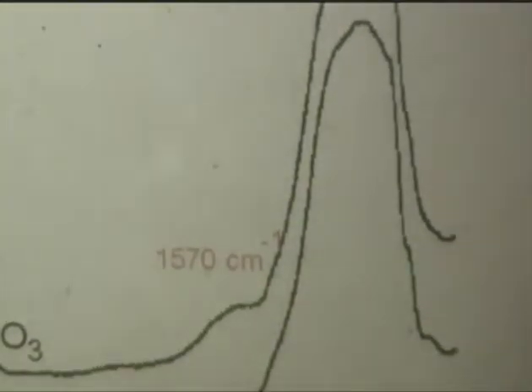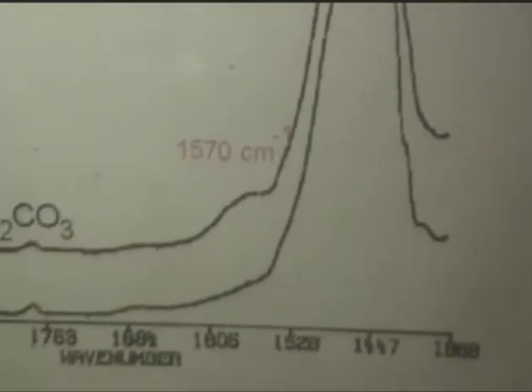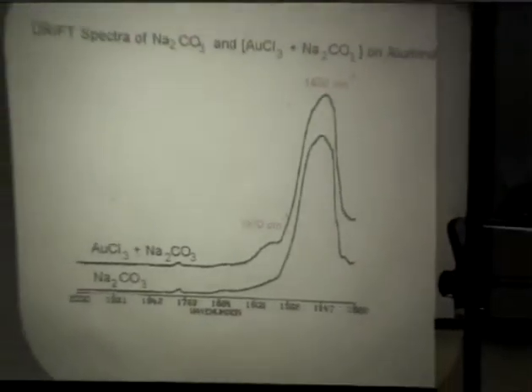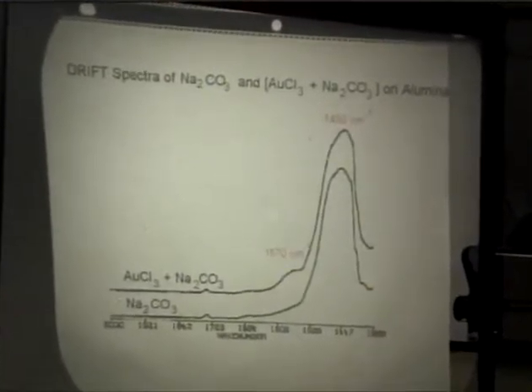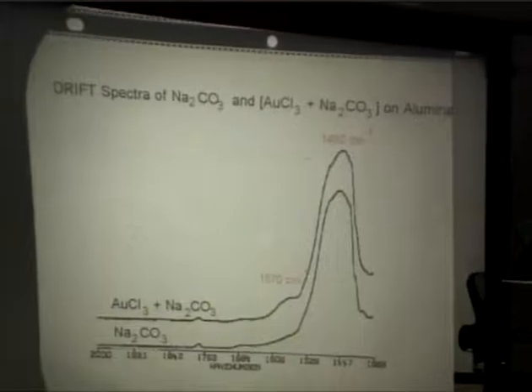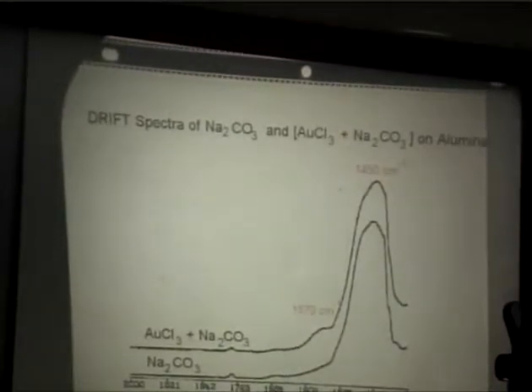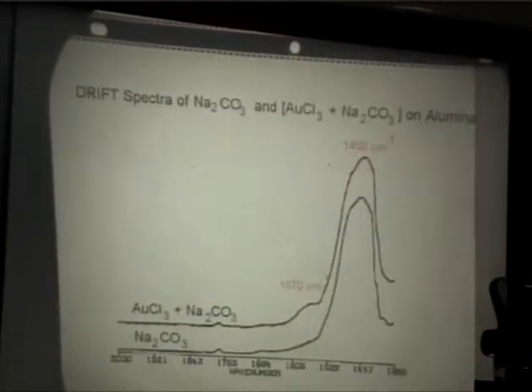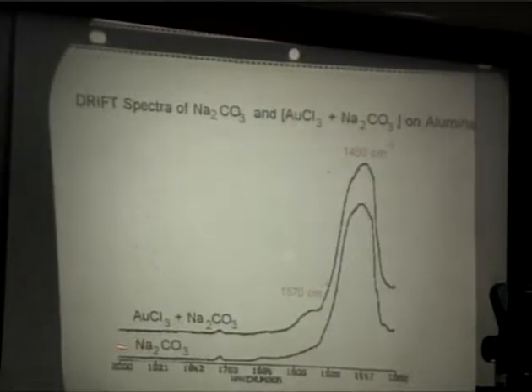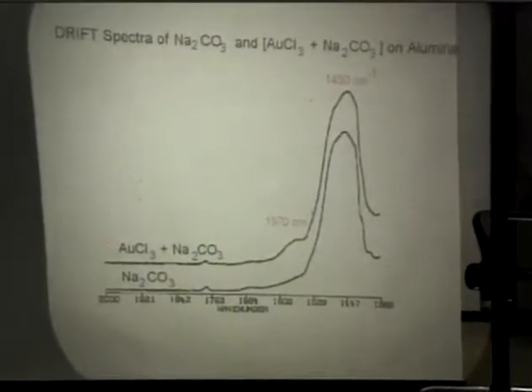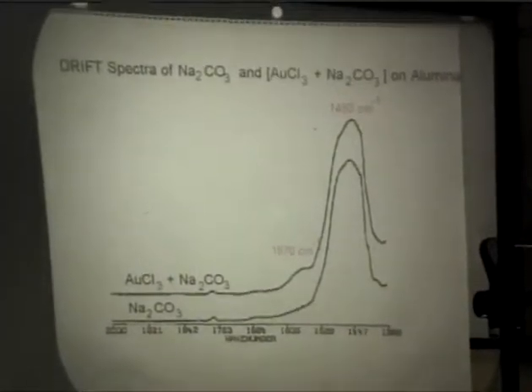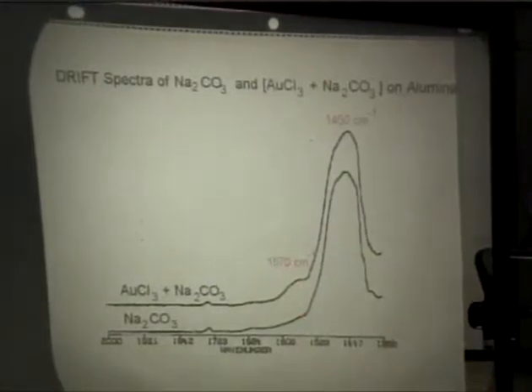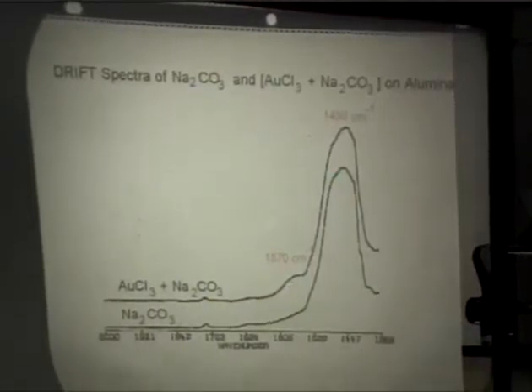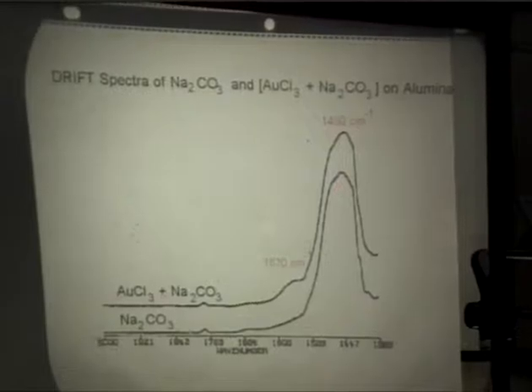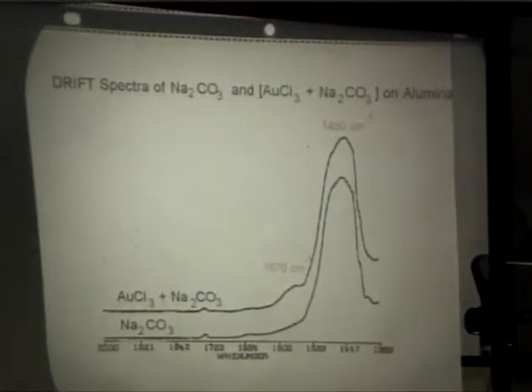Another way to look at it is to take it and look at it with diffuse reflectance infrared. You can expect that if you're making some type of metal carbonate, it would have an interesting absorption. What we see here is this 1450 wave number is the sodium carbonate absorption. If we titrate that with gold chloride, we see a band or shoulder form here at 1570, and then we have an excess of carbonate here that's still apparent at 1450.